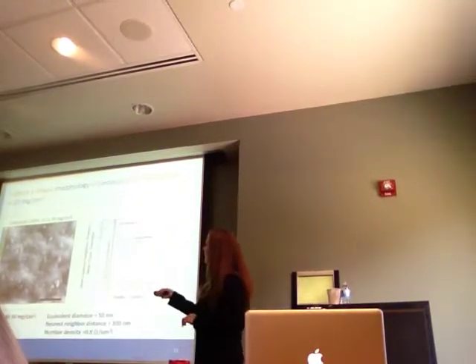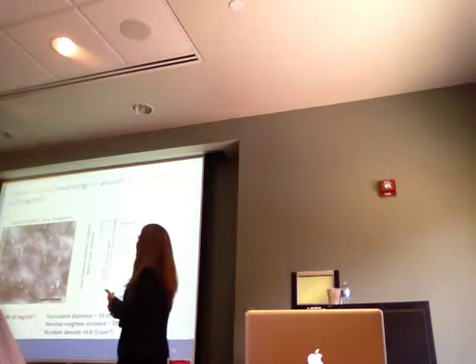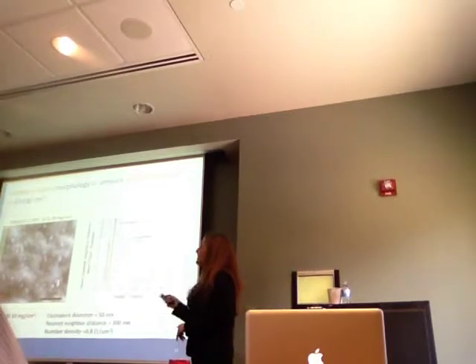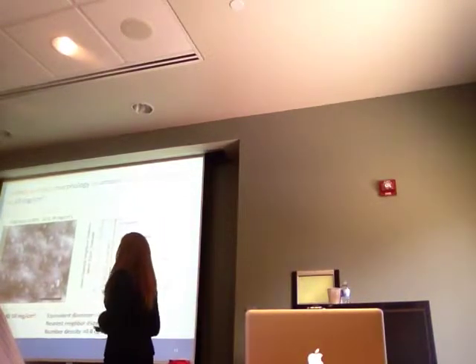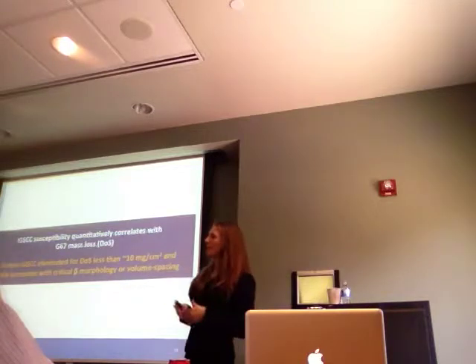Now another study was able to open up the grain boundaries of 5083 with a liquid gallium embrittlement mechanism, and so they were able to see the actual grain surfaces and look at all the particles on the grains. They characterized these particles by the size and the spacing, and put together this ratio of the nearest neighbor distance and the equivalent diameter, the spacing over the size, and they saw that at 10 milligrams per centimeter squared, there was a nice drop in the ratio, which was mainly due to the size of the precipitates increasing. So again, at 10 milligrams per centimeter squared, there could be a correlation with the size, the spacing, or the morphology of beta phase. So, quick takeaway point to that section.